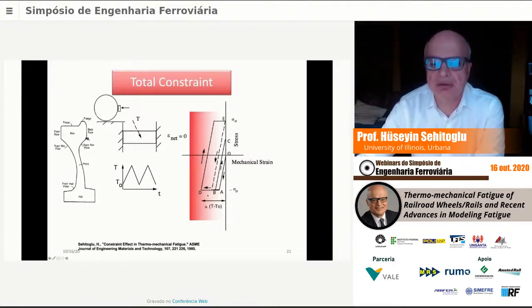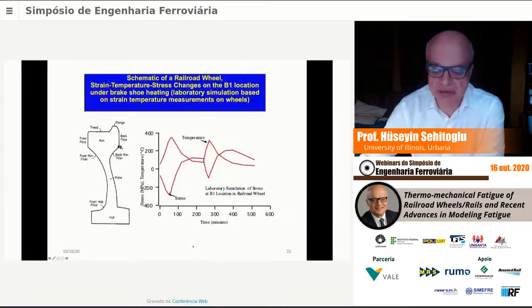If you heat back up again, you go along the dashed line, and then you heat, you cool, you heat, you cool, and you get this hysteresis, and you could get thermomechanical fatigue here, clearly. This is called total constraint, the way the picture is, and this plot is stress versus mechanical strain. Because the net strain is zero, the mechanical strain is equal and opposite to the thermal strain, right? So all of the thermal strain is converted to mechanical strain. Mechanical strain is negative, and you're hot here, and you are in compression. So this is an out-of-phase loading, right? The maximum temperature and minimum strain coincide in this case. Some of these concepts are explained in this paper.